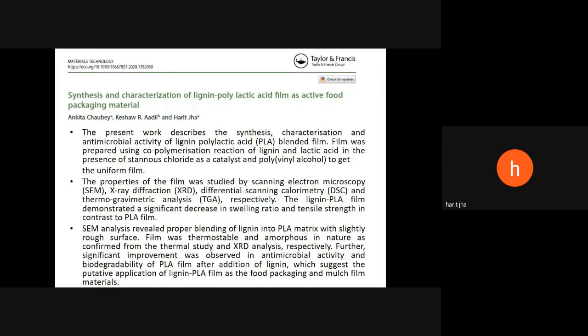This was the outcome of another project in which a lignin polylactic acid film was synthesized using stannous chloride as one of the catalysts, and it was studied using SEM, XRD, DSC, TGA, etc. We found that the lignin and PLA matrix has a slightly rough surface, but the film was thermostable and amorphous in nature. Significant improvement was observed in antimicrobial activity and biodegradability of PLA film after addition of lignin, which suggests the putative application of lignin PLA as food packaging and mulch film material.